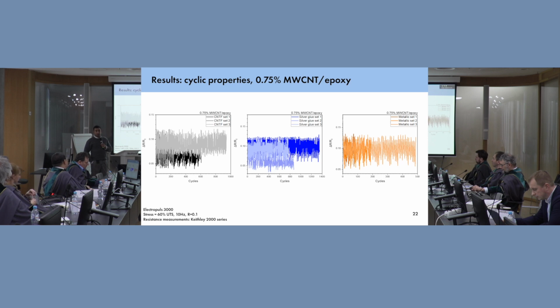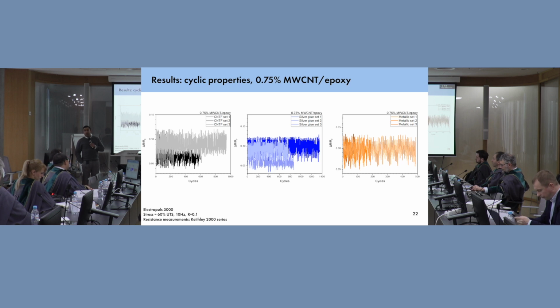However, we are using commercial materials here. Commercially, carbon fiber, when it's produced, it is produced with a sizing, a layer of ceramic, let me say, powder, which is there to protect it during transportation and shipping. To remove this sizing and this addition of polymer, you need to use some chemical techniques. And during the usage of these chemical techniques, there is a high chance, at least with people who do not have experience with it, such as myself, to damage the fibers. So it really wouldn't be as good as the results I would have for the metallics. This is exactly one of the things that we have noticed. It was raised by my IDC members as well, by Dr. Stanislav Ivlashin. We will continue in this direction, but first I need to understand how to remove the sizing properly.